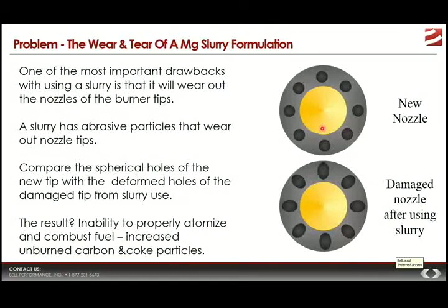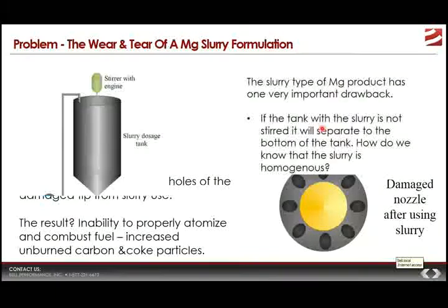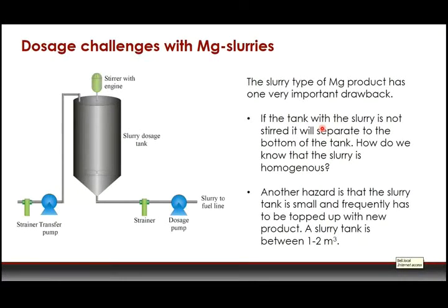The basic downside is that if the fuel's not atomized properly, it's not going to burn properly. They're going to get higher levels of unburned carbon and higher levels of coke particles that are formed. Another challenge with magnesium oxide slurries: they typically have to have their own dosage tank, and the dosage tank has to have a stirring mechanism in it because magnesium oxide slurries will settle. If you've ever been cooking and mixed up a flour water slurry, same kind of thing. You leave that for a period of time, all the flour is going to drop down to the bottom. You have to circulate it and mix it up to ensure that the particles are homogeneously distributed.